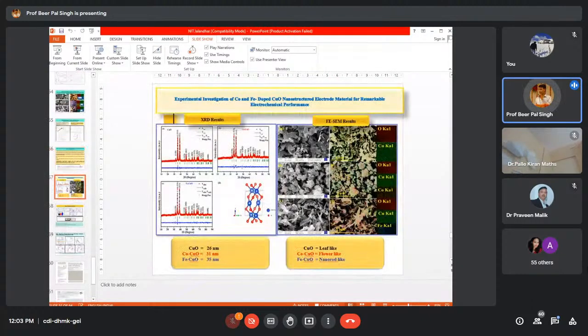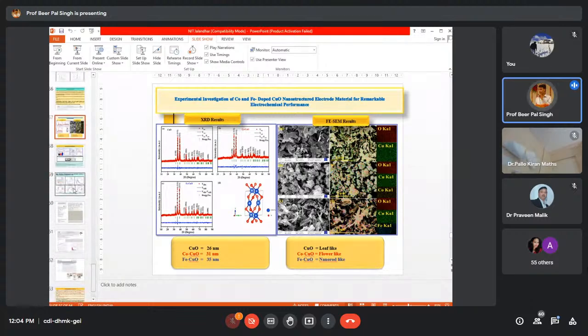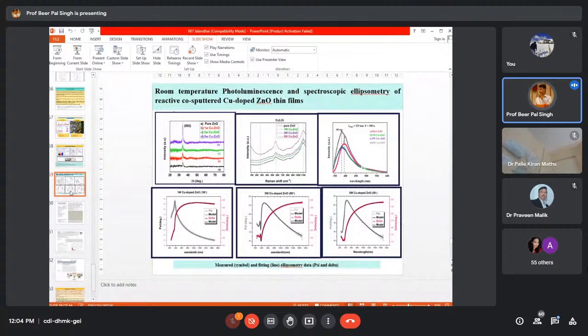She also made Co and iron doped copper oxide nanostructures, again fabricated using the hydrothermal method. She used this material as an electrode material in supercapacitor application and found remarkable electrochemical performance. One of my students recently deposited copper doped zinc oxide thin films by sputtering and studied photoluminescence and spectroscopic ellipsometry of this material, and published the results in a very good journal, namely Optik.